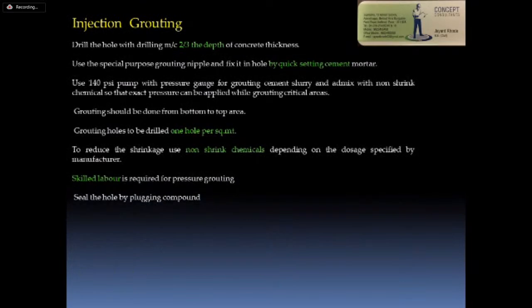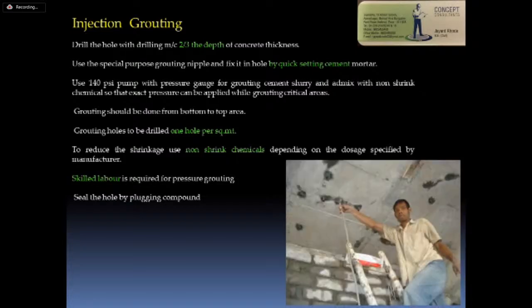Injection grouting, this is a cement slurry grouting. You use cement, you use water, some few chemicals are added in that mixture to make a slurry, and inject that slurry by gravity grouting or by machine grouting. There are a few pumps available in the market with which you can inject a cement slurry which will go into the concrete structure and seal the porosity in the concrete, and on the other hand you will get the waterproofing. I'll show you a video here.